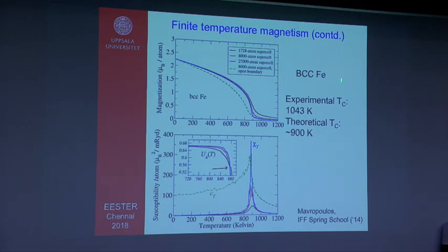So if you look into the experimental value for the critical temperature, that's the Curie temperature, it is 1043 Kelvin for BCC iron, and here from these simulations one can find it is around 900 Kelvin. So this is not too bad, this is pretty okay, but these numbers depend crucially on the details of your simulations. For example, what is the exchange correlation functional you are using, whether you are using LSDA or something beyond LSDA, taking into account electron correlations or not. But there is a huge effort that goes on in this field, and this has become quite a standard way of looking into finite temperature magnetism. People do it quite regularly.